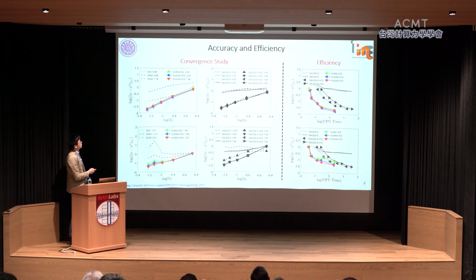So here are the results. You can see that for both nodal integration and Gaussian integration, I show a rate of convergence of 2 for both regular and irregular discretization. And also, of course, nodal integration shows much better computational efficiency than the Gaussian integration.